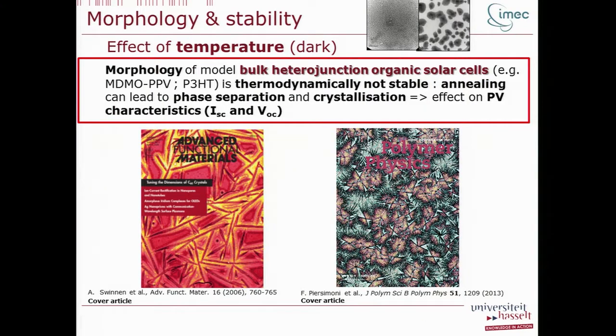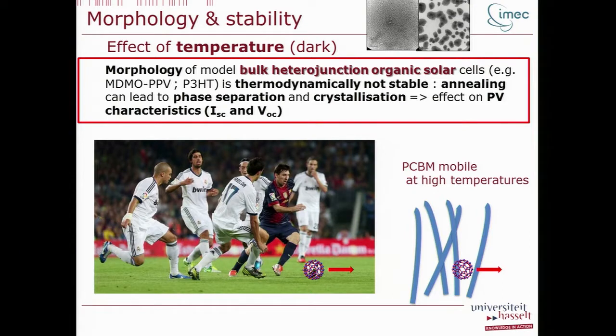For the polymer fullerene organic solar cells, also there we have known for several years that temperature can lead to significant changes of morphology, where we have, for example, big needles forming. Where are these needles coming from? Well, these needles come from PCBM. PCBM can be quite mobile at high temperatures.